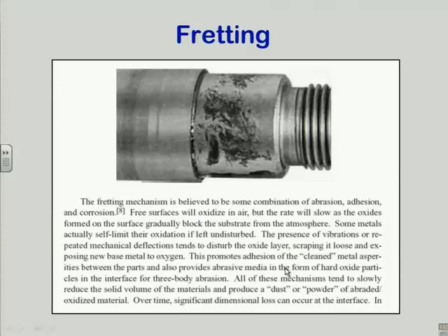After the machine has run for some period of time, months, years, whatever, I walk by one day and I look down and I say, that's odd. All around that pin is some red stuff. And I take my finger and pick it up, and it's gritty. It's iron oxide. It's rust. And it's coming out of the interface between the pin and the machine. And there's probably some oil mixed with it because there's oil all over the place in the machine. So what I have is oily rust, which is abrasive as all get out because iron oxide is a ceramic. It's harder than steel by a long shot. And it's forming in the interface of the press fit. And the mystery is no one knows quite what makes it form.